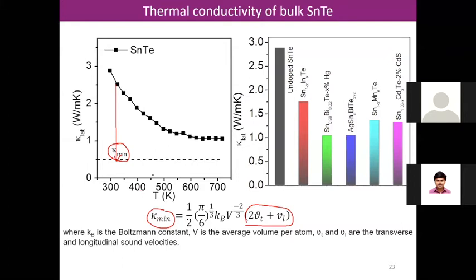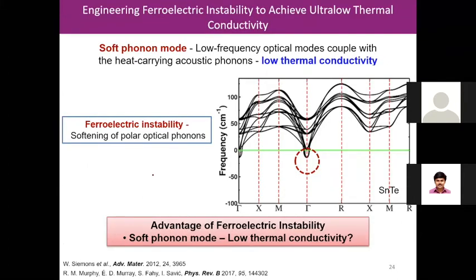Okay, so for low thermal conductivity we need soft optical phonon modes. Soft means low energy optical phonon modes, as we saw in the last example. So we have to have very low energy, soft vibrations. Now another field, I'm sure some of you know, is ferroelectricity, and ferroelectricity generally arises in a material from softening of a polar optical phonon. Now we can see the phonon spectra of tin telluride.